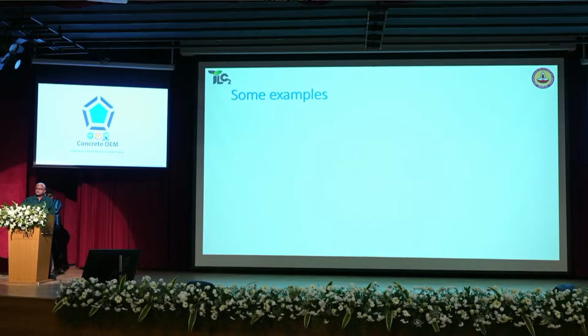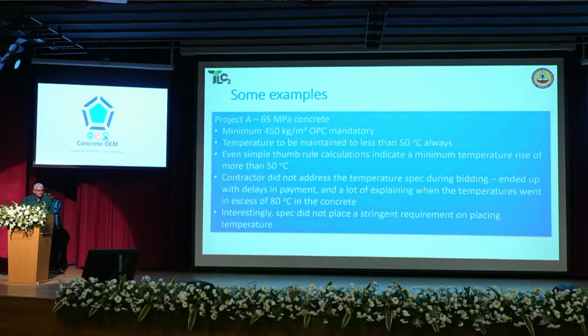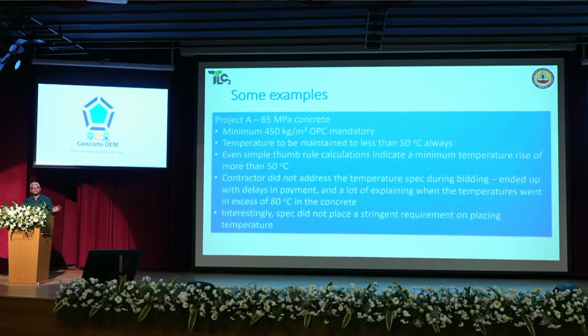Some examples of specification challenges and what kind of issues came up because of that. There's one project, I'm not going to name any of these projects, they're just some projects where I was involved in one way or the other. Here in this project, about 65 MPa concrete was being designed. And as per the spec, a minimum of 450 kilograms per cubic meter of OPC was mandatory. It's not cementitious content. 450 kilograms of OPC was mandatory, right?